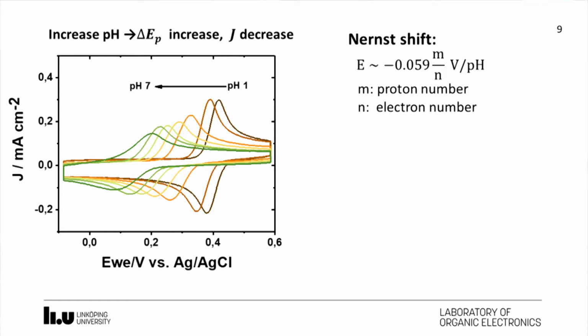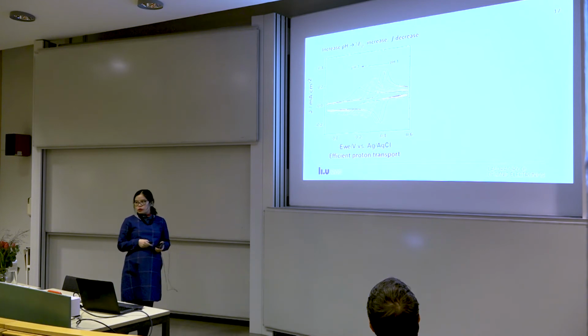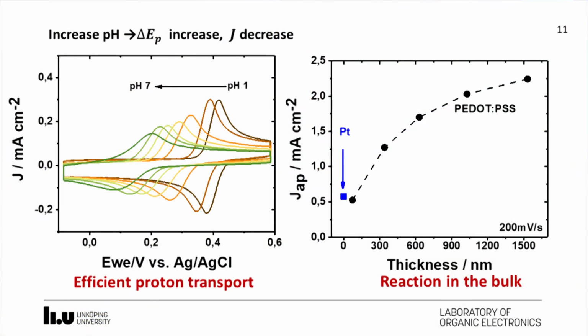But we also observed that the peak-to-peak separation increases and the peak current decreases. So when the proton concentration in the electrolyte becomes lower, the reaction rates also decrease, which further emphasizes that efficient proton transport is super important for these two proton-coupled electron transfer reactions, which makes PEDOT:PSS superior to the other electrodes.